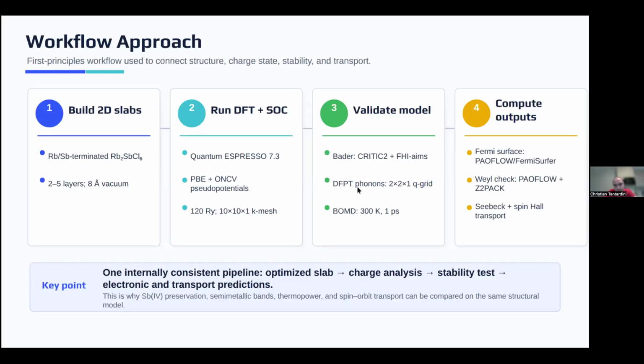We have also performed density functional perturbation theory (DFPT) to see the phonons, to see if it's possible to synthesize. We have also performed Born-Oppenheimer molecular dynamics to see if it is also dynamically stable, so it's not only at 0 Kelvin and 0 pressure. And we also looked at the Fermi surface. We checked, and you will understand later why, whether there were Weyl points, and we also measured Seebeck and spin Hall transport.